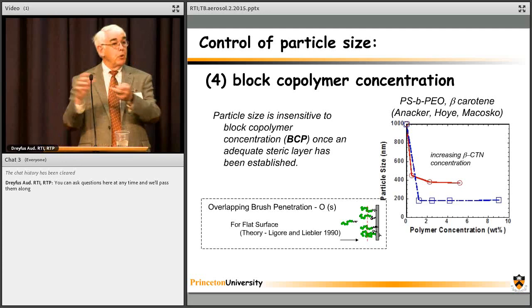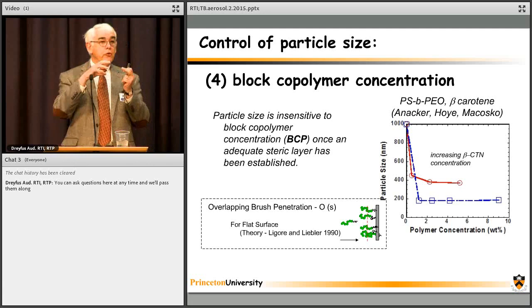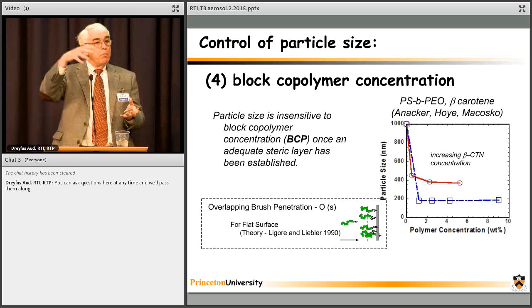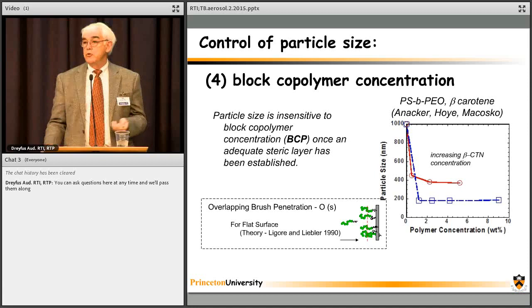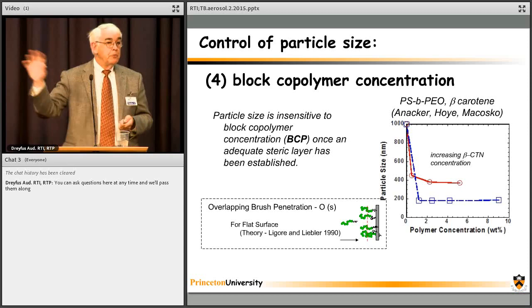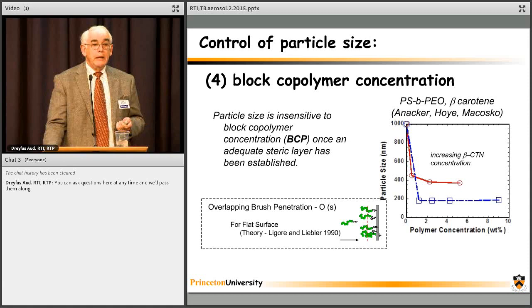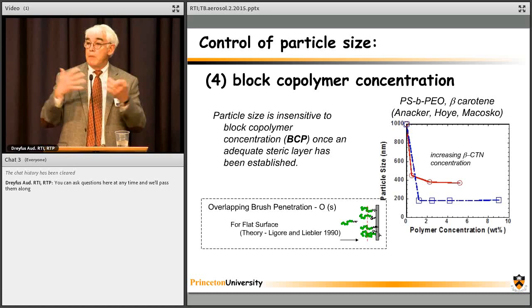What happens is that polymer adsorbs, accumulates on the surface until that head layer, that PEG layer, is densely packed. And at that point, no more polymer can adsorb. And so now the excess polymer you add goes off to form those micelles I showed you. So once you have saturated the surface, adding more polymer doesn't help. It just makes more micelles, which are not helpful in the process. So it's controlled mainly by the supersaturation and nucleation rate, and not primarily by the polymer. The polymer is crucial for stopping aggregation, but it's not setting the nanoparticle size.